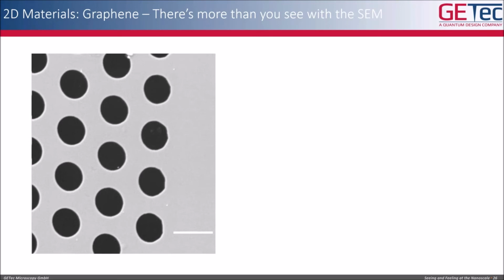But before I come to the results, I want to show you that there's really more than you typically see in the SEM if you have an AFM integrated. This is an SEM scan, the highest resolution we can achieve in our demo system, which is of course not the latest version of the SEMs, but you barely see anything of these 2 or 3 monolayers of graphene covering these holes.